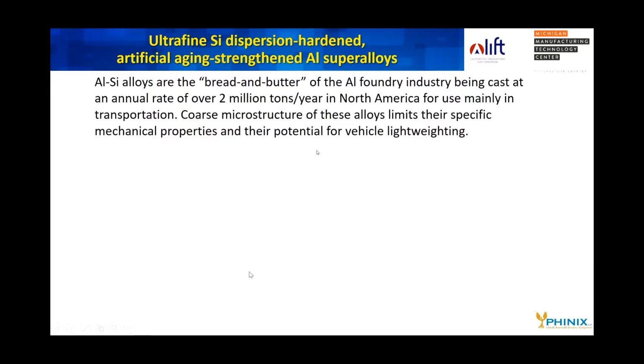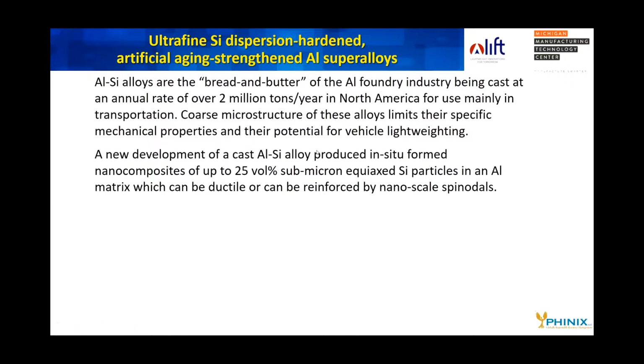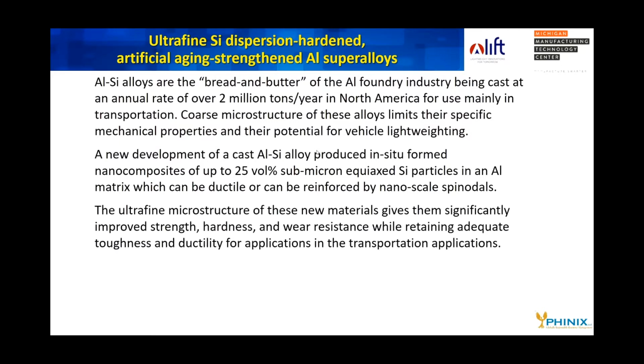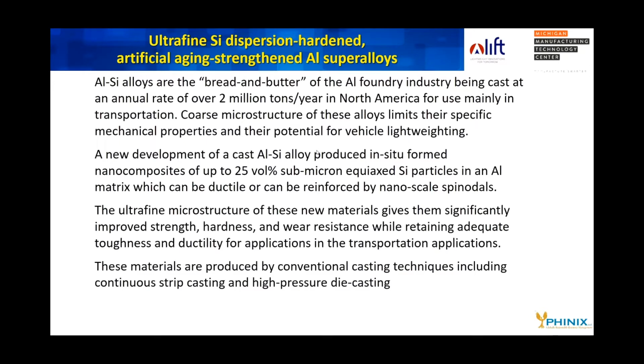A new development is a cast aluminum alloy produced in situ as a nanocomposite of up to 25 volume% of submicron silicon particles in an aluminum matrix that can be left ductile or can be reinforced by nanoscale spinodal precipitates. The ultrafine microstructures of these new materials give them significantly improved strength, hardness, and wear resistance, while retaining adequate toughness and ductility for transportation applications. These materials are produced by conventional casting techniques, including continuous strip casting and high-pressure die casting.